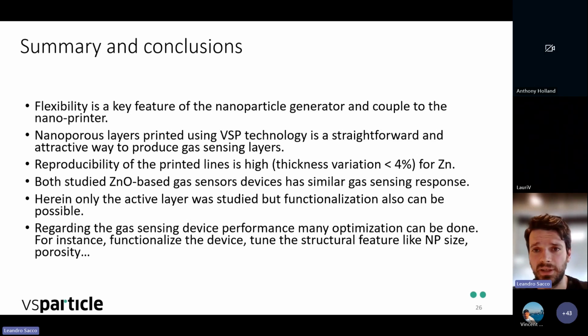Here we show that if we print different lines at identical printing parameters, the variation is below 4%. This is reflected also in the gas sensing performance of these devices. They were very similar. And as I mentioned before, there's still a lot of room to improve, because we can functionalize this device to be more sensitive to toluene if you want. We can deposit some catalyst, for example, or we can tune the parameters involved in the spark ablation in order to get a higher porosity or a smaller nanoparticle size. We can do different kinds of oxidations. So there is a lot of room to improve this kind of devices.